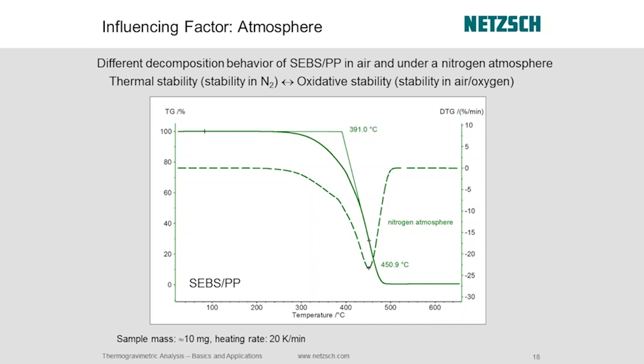So what we're going to look at is this SEBS polypropylene compound, both in air and under a nitrogen atmosphere. In nitrogen, we're looking at thermal stability. Sometimes in the polymer sector they'll also say pyrolysis, so you could probably use that term here as well, because we're basically looking at thermal stability in nitrogen, and we're going to compare that to how the material behaves when we run it under air.